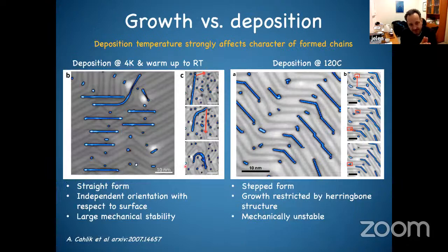Another thing is that we also see different structures when we deposit these molecules. The same molecule, but now deposited at a slightly elevated temperature. And now what we start to see is that instead of being very straight, they start to be zigzag. There are many defects here. They are no longer straight like this, and they also respect the herringbone.